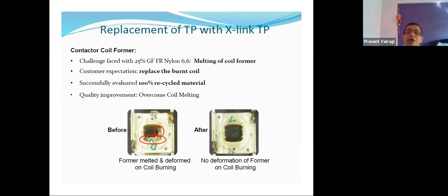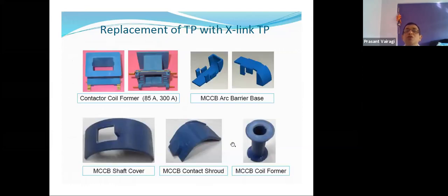This is the contactor, again another rating of the contactor. You can see after the short circuit condition, the former has burned. But this is thermoplastic, and it has not melt deformed, because if it melt deforms, it will cramp the entire contact assembly, which is not desirable. Okay, modified thermoset composite, another case with polyurethane with certain combinations. We wanted continuous use temperature 120, CTI 1000 volts, arc resistance above 120 seconds, breakdown voltage, and so on. Based on all those properties we decide.